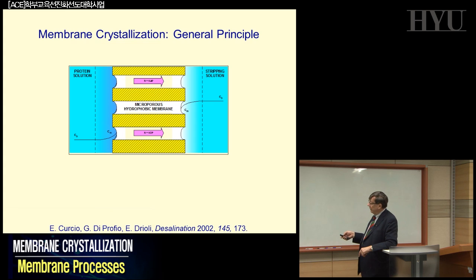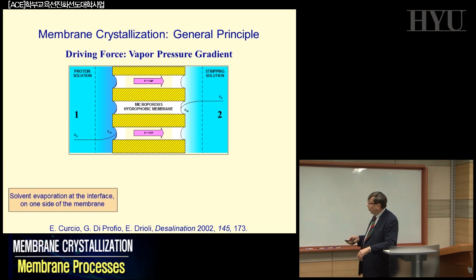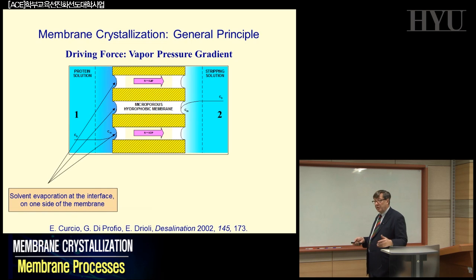Basically, the idea was that you can have an aqueous solution. At the interface, you can have evaporation of the solvent. No protein will go into a vapor phase. And if you have a small delta T, a few degrees centigrade, then vapor will go across, just water, and you will just recondense it on the other side. So easy, simple, and just an extrapolation of the concept of membrane distillation to the extreme case.